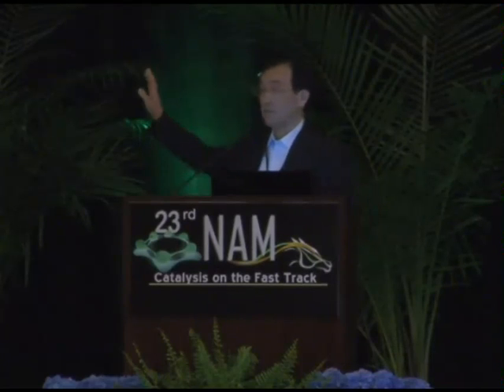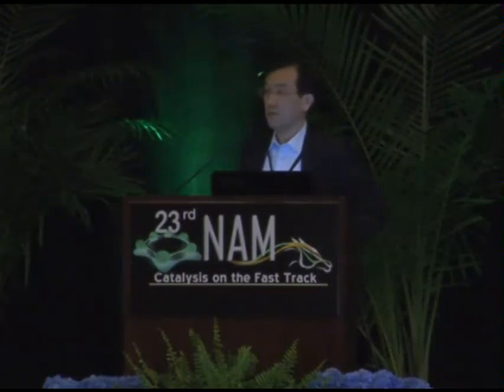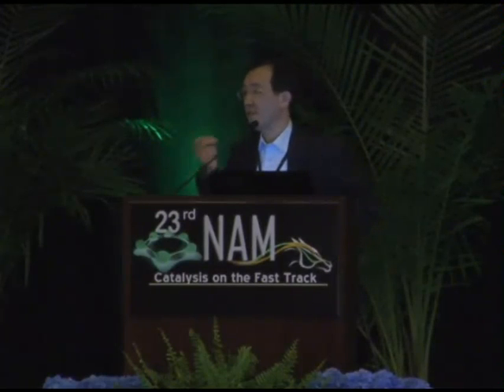Your acid site or the other acid site, you mean? No, just the acid site. You didn't see any desorption peak from the ammonia TPD? Ammonia TPD? Yeah, we did it. We didn't observe any weak acid site or strong acid site in the ammonia TPD profile. So this is the result of ammonia TPD. So no L peak or H peak appeared in the ammonia TPD. So the carboxylic acid is a very weak acid site.